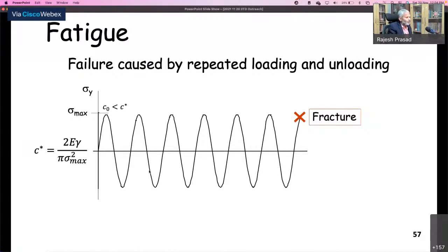But then what really happens is what is called subcritical crack growth. Even though C0 is less than C star, with repeated cycling, repeated loading and unloading, the crack is actually growing. So after some time, it is C0 plus delta C. It is still less than C star. The crack will not propagate fast, so you will not realize.